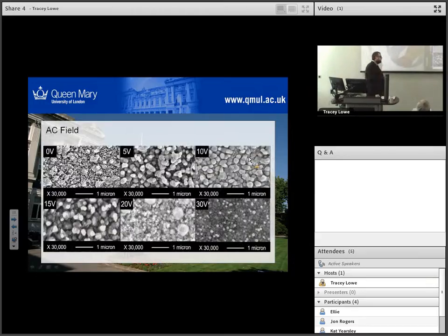So what happens? If we don't apply any field, we get this normal, fairly standard island growth, agglomerations and gradual growth as things go on. If we apply, in this case, an alternating electric field at 50 Hertz, you can see that as we increase the field we start to see some different pseudo-structuring, and then at some point we see a change in our growth mechanism, and something completely different.